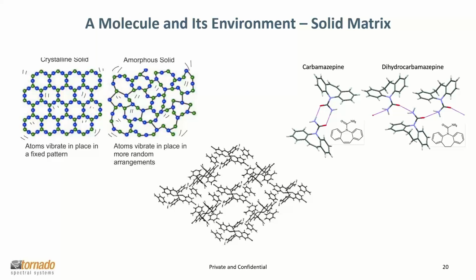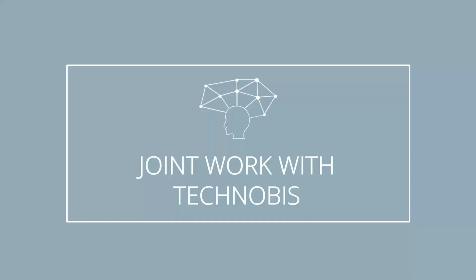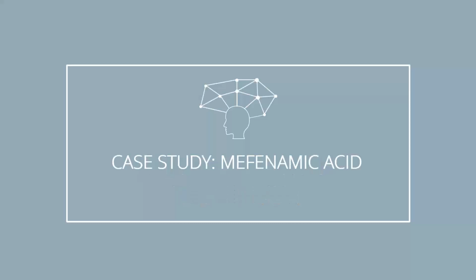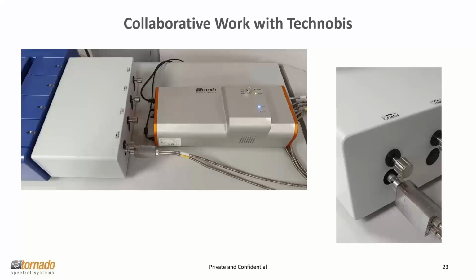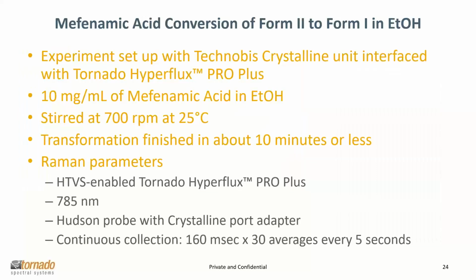And you can extend that same argument to salts as well. So the Raman spectra become different as the crystalline matrix changes because the environment of the functional group changes. So Thomas described a couple of experiments briefly that we did when we were using the Technobis device. And again, here's the setup that was used for the experiments with the Tornado instrument interface to the Technobis crystalline.